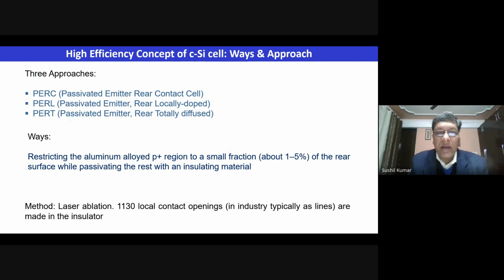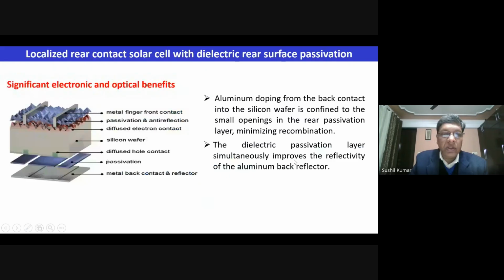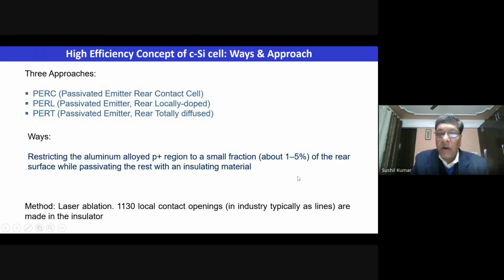And restricting the aluminum alloy P plus region at the rear side to a small fraction, about 1 to 5%. This is what I am showing here, 1 to 5%. It's not complete basically, and the rear surface, while passivating the rest. These are laser ablation, these grooves are formed with the laser. Typically for 6-inch cells it is shown, but nowadays M10 is also being used. Like 1130 local contact openings were made in the insulator. So this is how these innovations in the rear contact have improved the efficiency of solar cell.